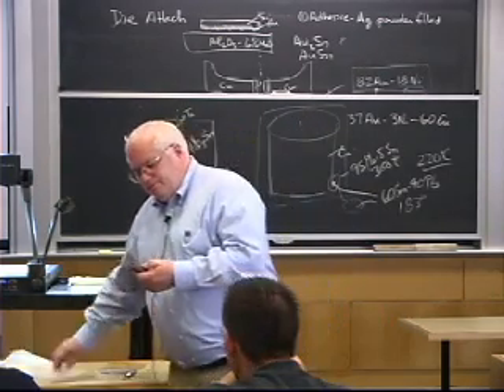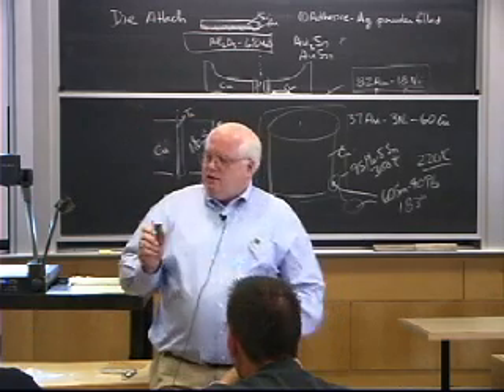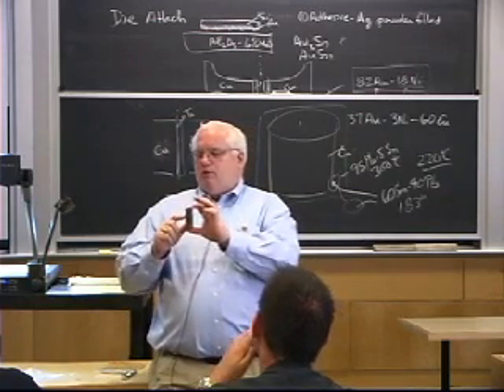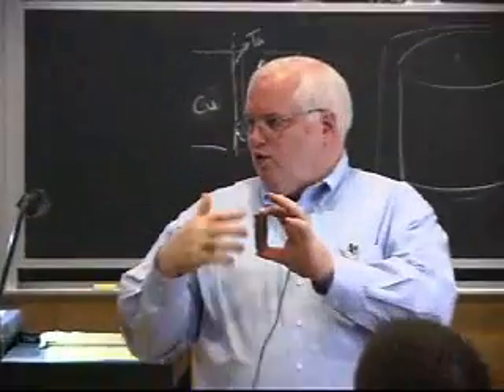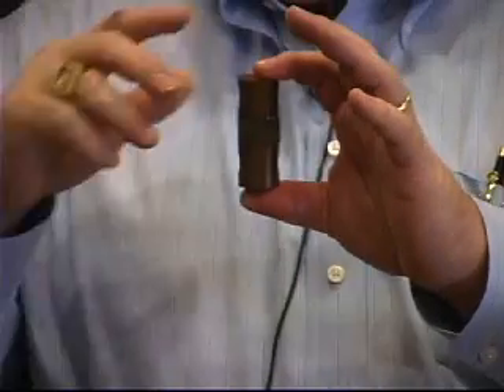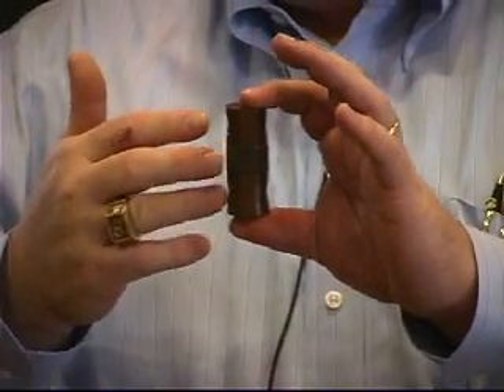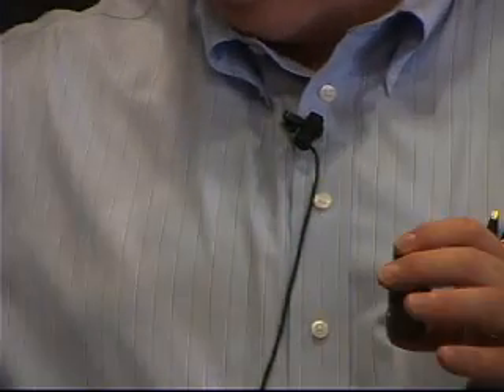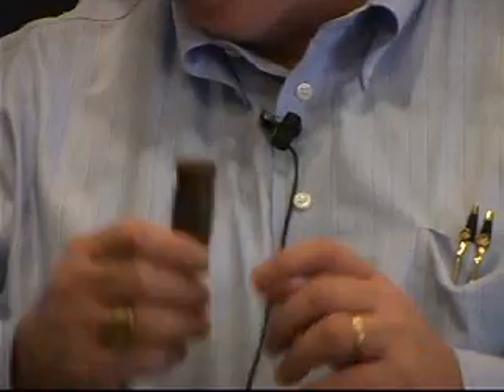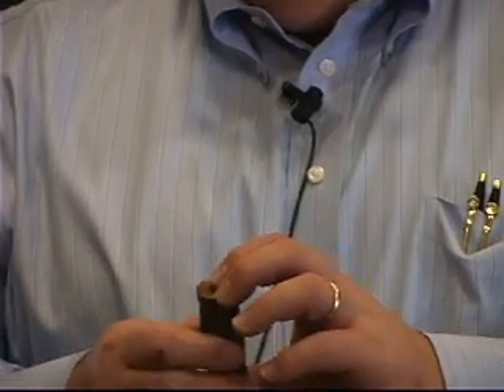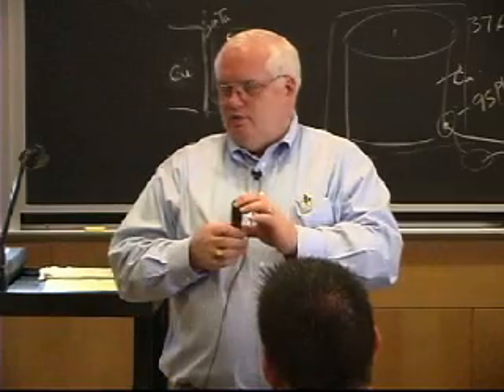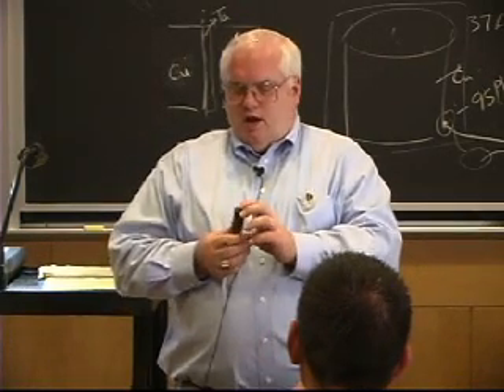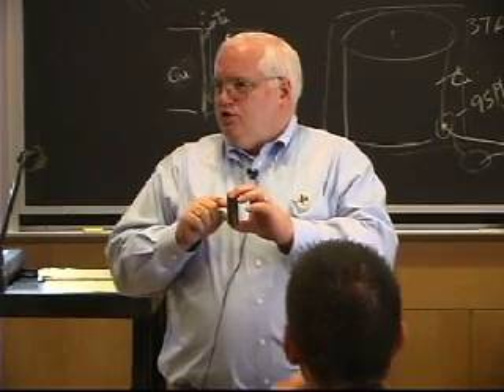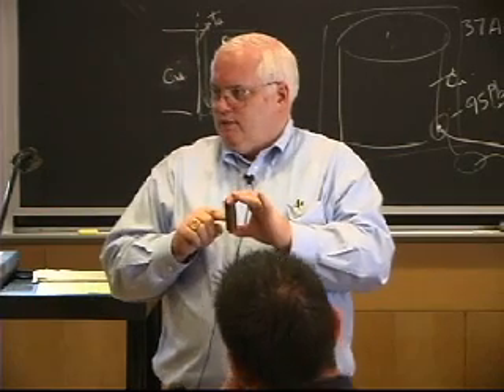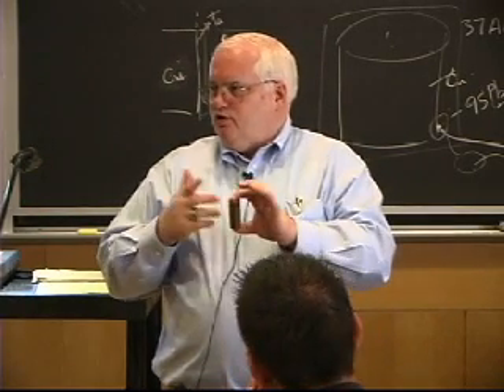This one is unusual in the sense that it's copper to copper, and we actually wanted to develop a way to bond copper bus bar, without heating everything up, and copper bus bar for big currents. This was over at the National Magnet Laboratory. Actually, this was for the fusion reactor experiment that they were running over there. They wanted a simple way to bond bus bar, and one of the things you could do is you could plate the whole thing with silver. And silver and copper form a eutectic, and you can make a nice little braze joint.